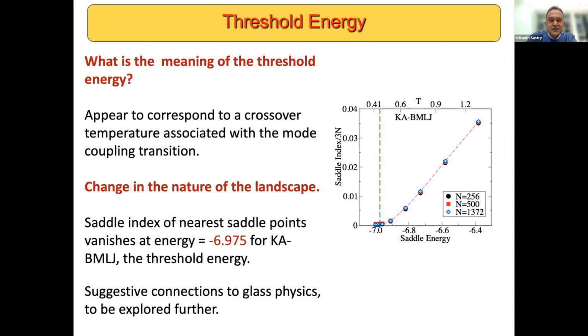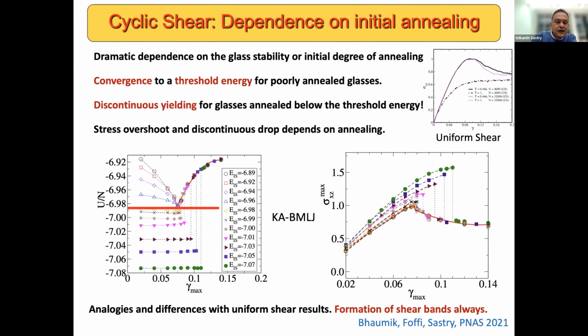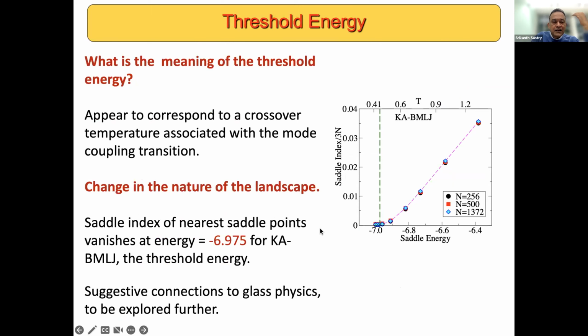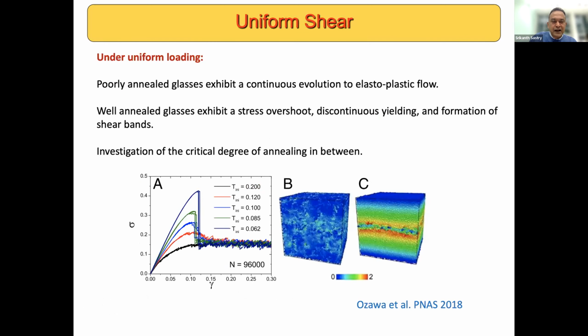Okay, now what this threshold energy is, is an interesting question. And we don't have very clear answers at this moment, but one analysis that we made shows quite clearly that the nature of the energy landscape is changing at the threshold energy we found by considering yielding behavior. So at this energy that corresponds to the red line, one has the vanishing of the saddle index of the nearest saddle points from typical liquid configurations. This is a very suggestive connection to glass physics, which needs to be explored further, but I won't talk about this now. And this is just to quickly show that the same kind of change in the yielding behavior has also been studied under uniform shear deformation.